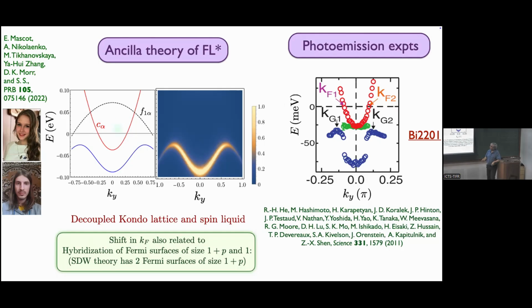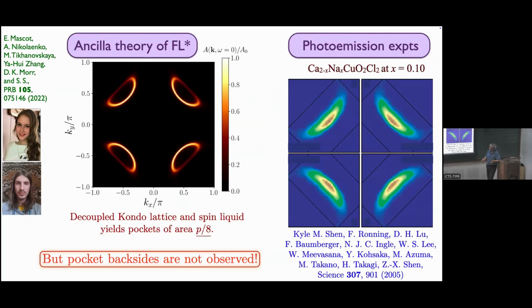But now you see that the Fermi wave vector of the F band is out here, the Fermi wave vector of the C band is here, because they have different densities. And in fact, the other one we need to take a whole lag to get the data to work out. And so the position of the minimum pseudogap is not the same as the Fermi momentum as was in this. So this paper emphasized the difference between Kf and Kg. And that's exactly what you get, the same kind of shape. So it all seems to work. At least at the antinode, it works beautifully. But on the nodal point, we're fitting the data, but there is definitely a backside.